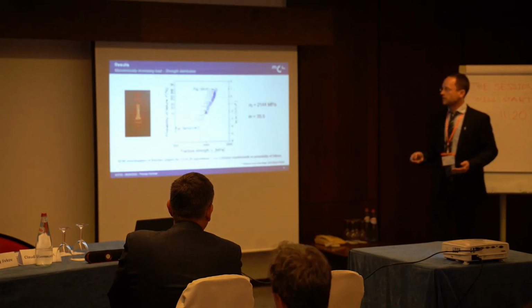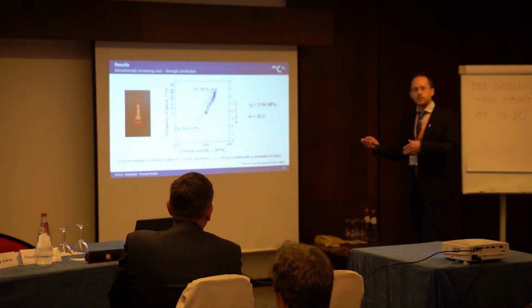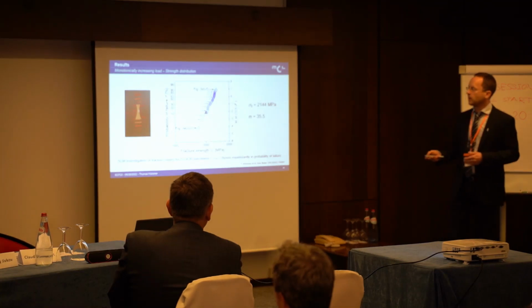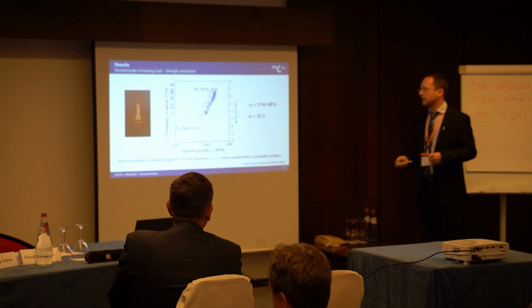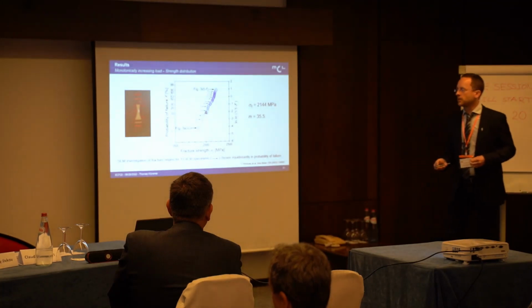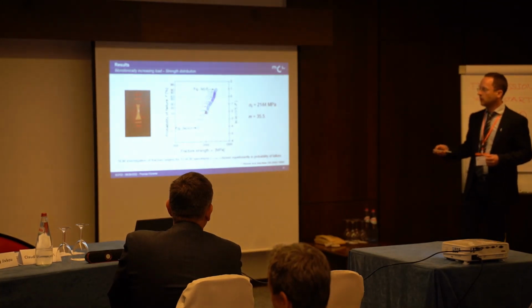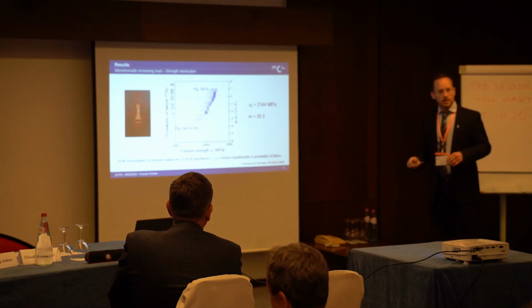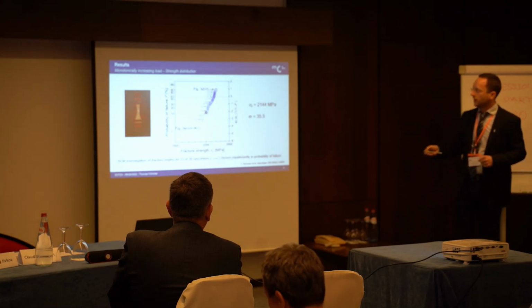Okay, so the results, what were they? We saw a certain distribution of fracture stress at elevated temperatures with a certain characteristic strength with a Weibull modulus of 35, which is rather high for this class of materials, I'd say. And we looked at the fracture origins of 13 of 30 specimens equidistantly chosen in probability of failure.